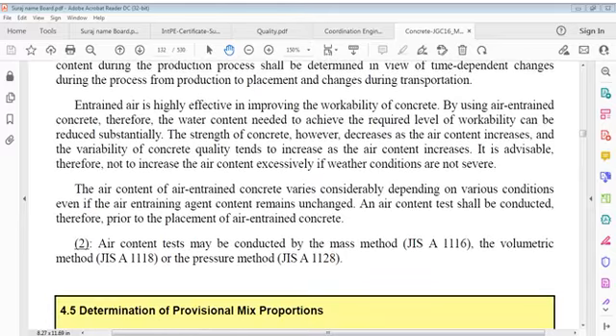Entraining air is highly effective in improving workability of concrete. By using air entrained concrete, therefore, the water content needed to achieve required workability can be reduced substantially. Strength of concrete, however, decreases as air content increases, and variability of concrete quality tends to increase as air content increases. It is therefore advisable not to increase air content excessively if weather conditions are not severe.